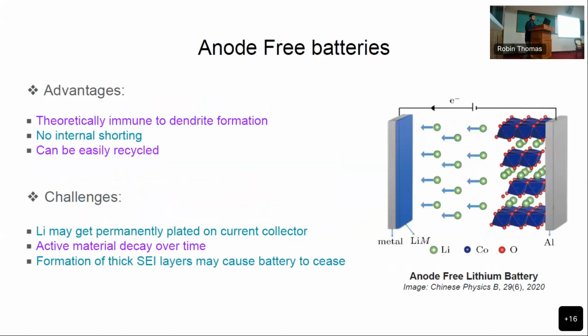And the advantages of these are theoretically immune to dendrite formations, because we would expect all the lithium that gets deposited on the current collector to come back to the cathode. We don't really expect anything to stick there. So if there's nothing on the current collector, there's no scope of dendrite formation. But in practical cases, it's not possible, as some lithium gets left behind and they serve as nucleation sites. There's no internal shorting because it just has one electrode, doesn't have two, and can be easily recycled.